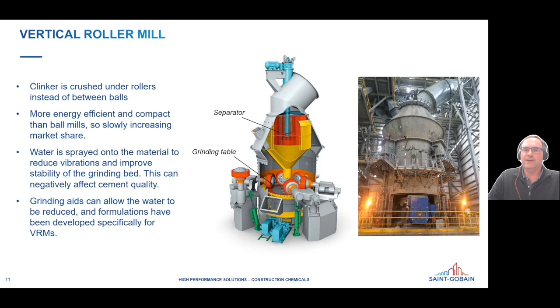So you normally have to add water spray onto there in order to reduce the vibrations. And you can actually spray less water if you're using a grinding aid, which helps improve the quality of the cement. In fact, many grinding aid companies have developed formulations that are specifically designed to work well in a VRM.